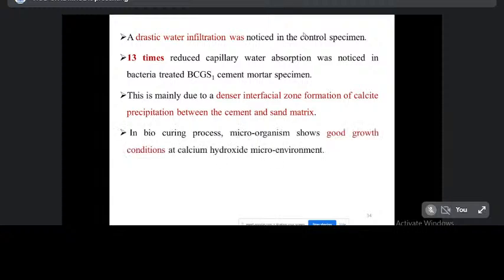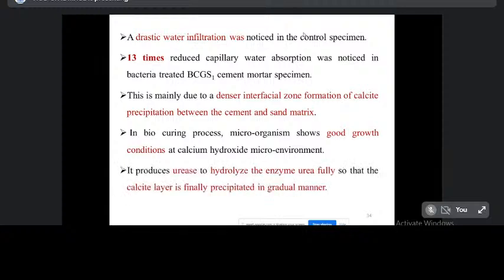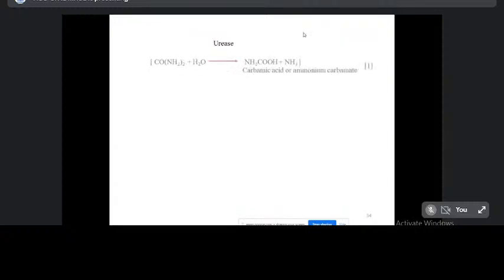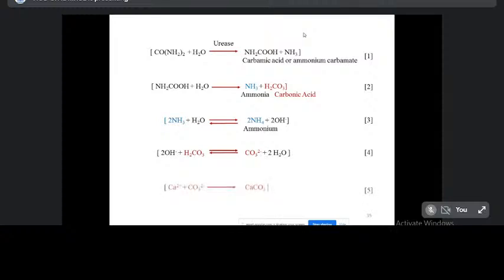In the biocuring process, the microorganism shows good growth condition in the calcium hydroxide microenvironment. It produces urease to hydrolyze the urea fully so that the calcite layer is finally precipitated in a gradual manner. This is the chemical formula of formation of calcium carbonate. Actually, the bacteria produce urease. This urease is combined with atmospheric carbon dioxide. Finally, it is converted into calcium carbonate, CaCO3. This is the chemical equation involved in this process.